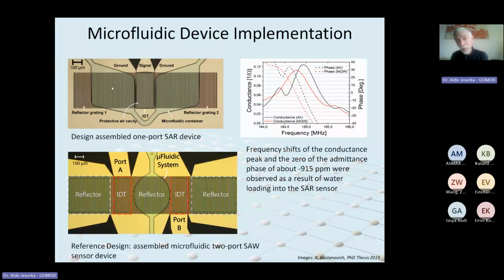It's a silicon rubber that can be used for imprinting channel structures, and it's bonded here. And what you see now here is that the signal has an air cavity on top of it so that it's not damped, and then it transfers the energy that comes here in the center into the IDT, and it's being then reflected back and forth, and the sample is sitting here on top of these reflector electrodes. So the energy that is stored here is basically being probed. Signal goes in and signal goes out, and while there's sample in these chambers, it has an influence on the propagation of the waves back and forth between the reflectors.